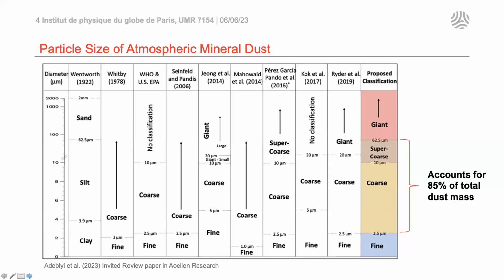They estimate in this paper that 85% of the total dust mass is probably between 2.5 microns and 62.5 microns. They also highlight in this paper that there's a very broad heterogeneity in how you quantify fine, coarse, and super coarse, so they propose this classification here of fine being PM 2.5, then coarse, super coarse, and then giant.